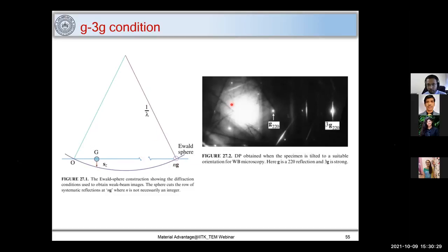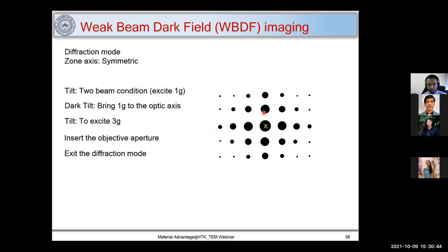And we are going for a G-3G condition. That means I have the first G spot, this is the 2G spot, and this is the 3G spot. So you can see here that I have excited this 3G spot as compared to the G spot. The intensity of the 3G spot is higher than the G spot. I will be looking at how we can do that.